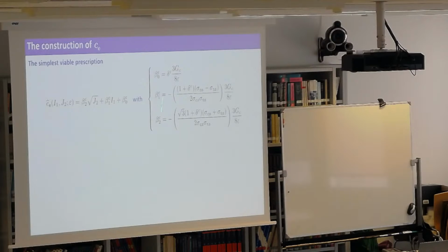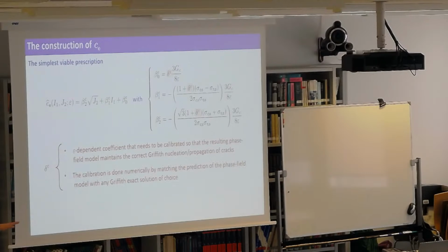So this is just an example. If the betas go like this, and there's a parameter here that I'm calling delta epsilon, then we will recover a strength as given, and this parameter is key. This is an epsilon dependent coefficient that needs to be calibrated so that the resulting phase field model maintains the Griffith propagation. If you don't put the right number there for a given epsilon, and you run propagation, you are going to get Griffith-like behavior, but with the wrong GC. So there is something that we need to calibrate, and we can only do it at this point numerically, right? We run the model, and we want to have agreement with Griffith, and that means that for a given epsilon and a given elasticity and everything, there is a unique value of delta, computed numerically, that makes this happen, all right?